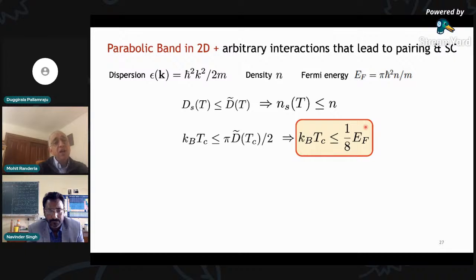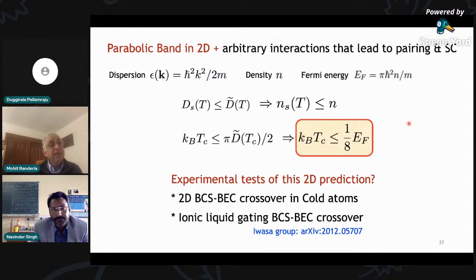But it leads to a rather remarkable result, which was never discovered until our paper: no matter what interactions you put in for a parabolic dispersion, the superconducting transition temperature can never be larger than 1/8 of the Fermi temperature. The reason this was never of any interest is that generally people were working with systems where the superconducting temperature was 3 or 4 orders of magnitude less than the Fermi temperature. So why bother about 1/8? The question is, are there places where we might test this, where the T_c might actually approach 1/8?